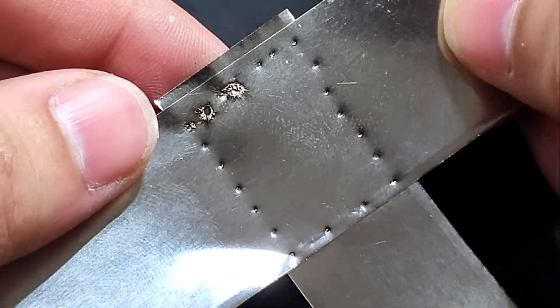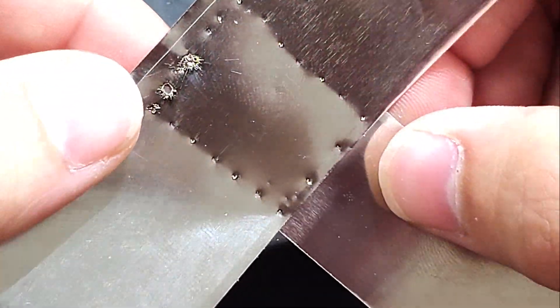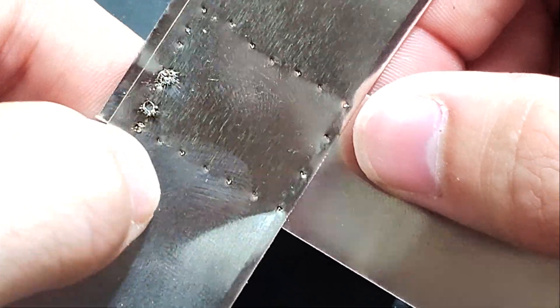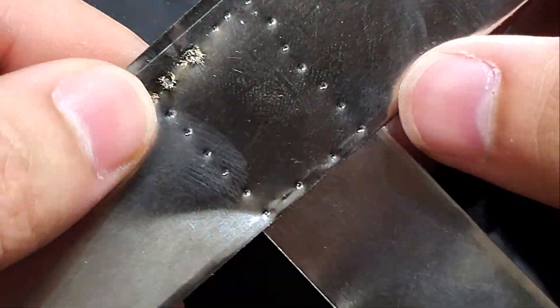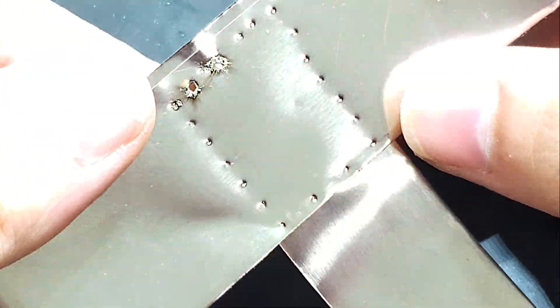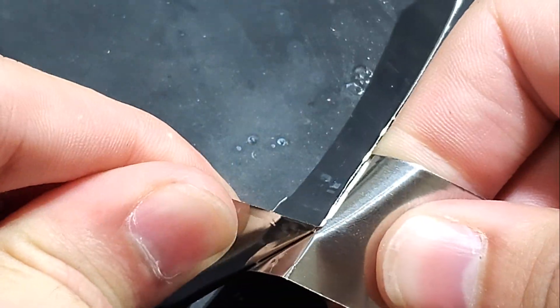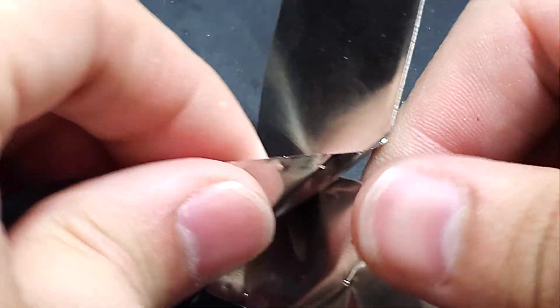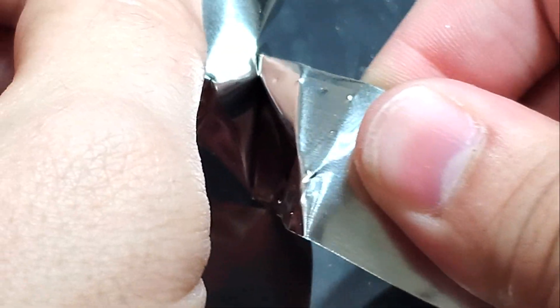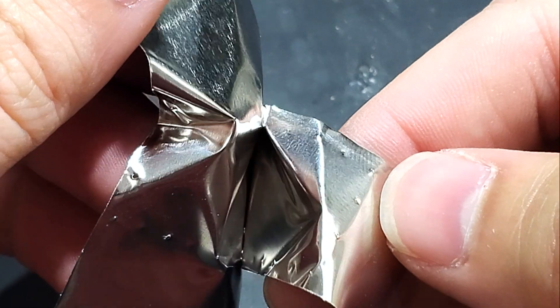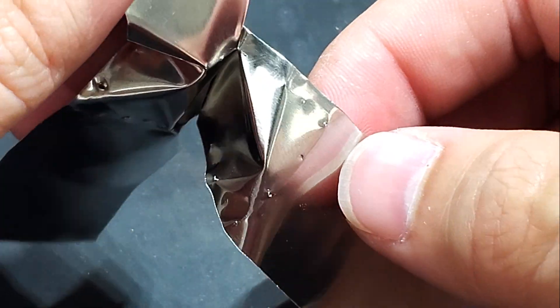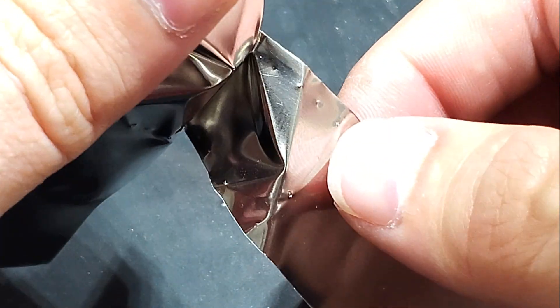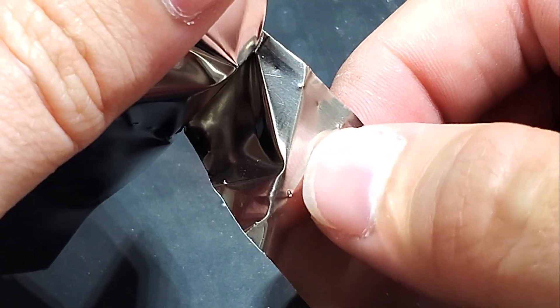As you can see applying about five pounds of hand pressure on both seem to yield some pretty clean welds. We'll just do a pull test really fast. So that's leaving nuggets behind which is a good indicator.